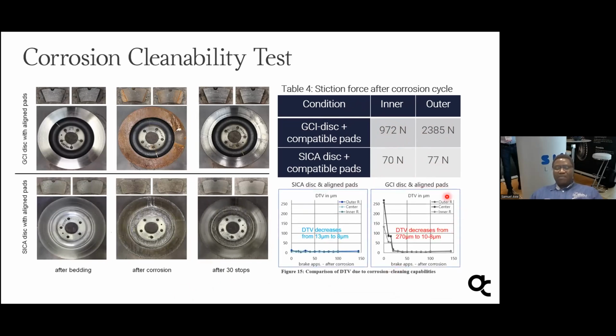In addition to that, we evaluated the DTV, that is disc thickness variation. For the aluminum rotor, it's very negligible. The DTV decreases from 13 micron to 8 micron. But for the GCI, it decreases from 270 micron to 10 to 8 micron. This will create the noise, what we call judder. It will create a lot of NVH issues due to this variation, because it will lead to vibration of the disc during the application, due to that variation in the DTV.